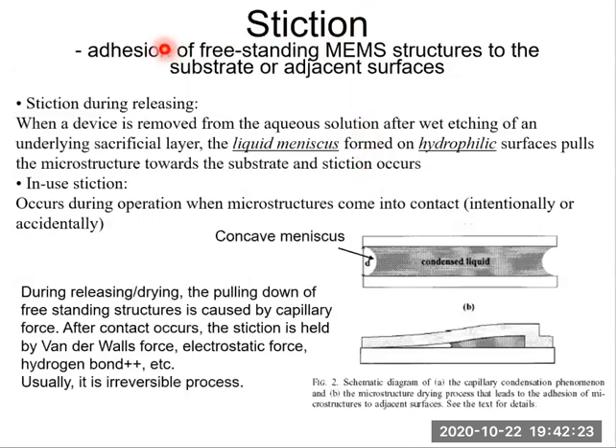Stiction refers to the adhesion of freestanding MEMS structures to the substrate or adjacent surfaces. Stiction is a serious yield and reliability concern for MEMS devices, especially for surface micromachined devices. Stiction can occur during releasing, when a device is removed from the aqueous solution after wet etching of an underlying sacrificial layer. So after finishing the sacrificial etching, we remove the device from the aqueous solution. Then the liquid meniscus formed on hydrophilic surfaces pulls the microstructure toward the substrate and the stiction occurs.